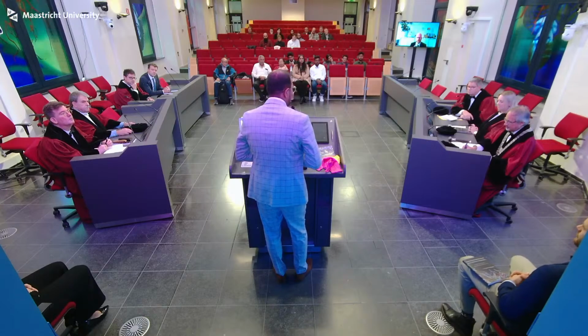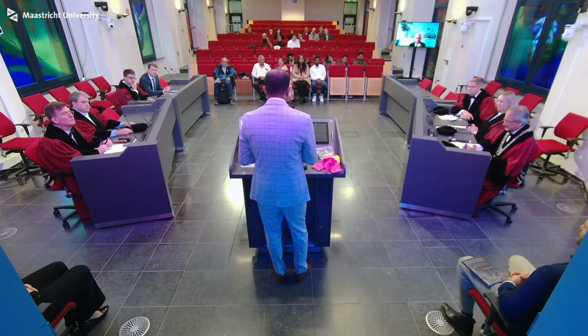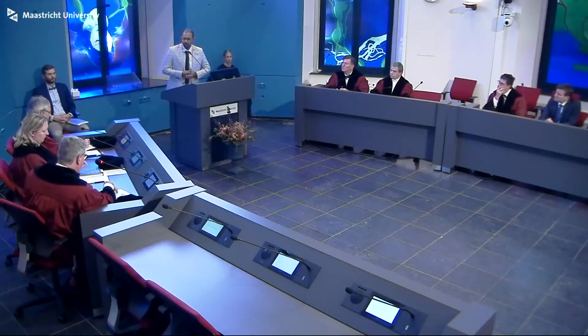Highly esteemed opponent, thank you for your question. Yes, we of course work, as I said, with melt electrospinning. In electrospinning, we need a polymer liquid, which is then pulled down using a collector plate to make a filament. In solution electrospinning, we work with polymer solutions. For example, with PLA, chloroform or dichloromethane could be potential solvents. Once roughly 8–10% polymer solution is made, it is pushed through the nozzle, and the filament is formed through evaporation of the solvent, and the polymer crystallizes as the solvent evaporates.